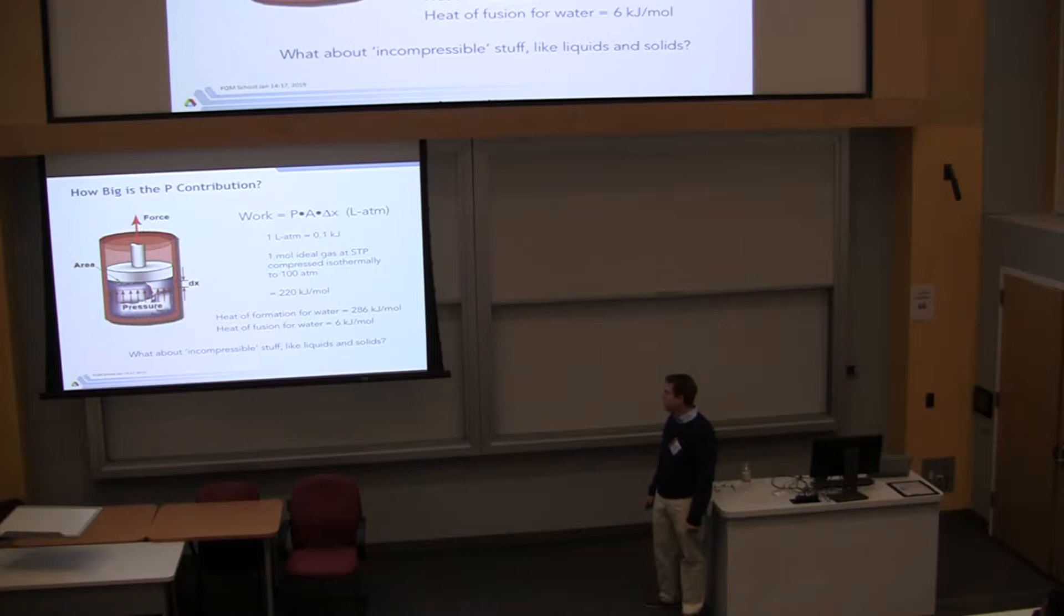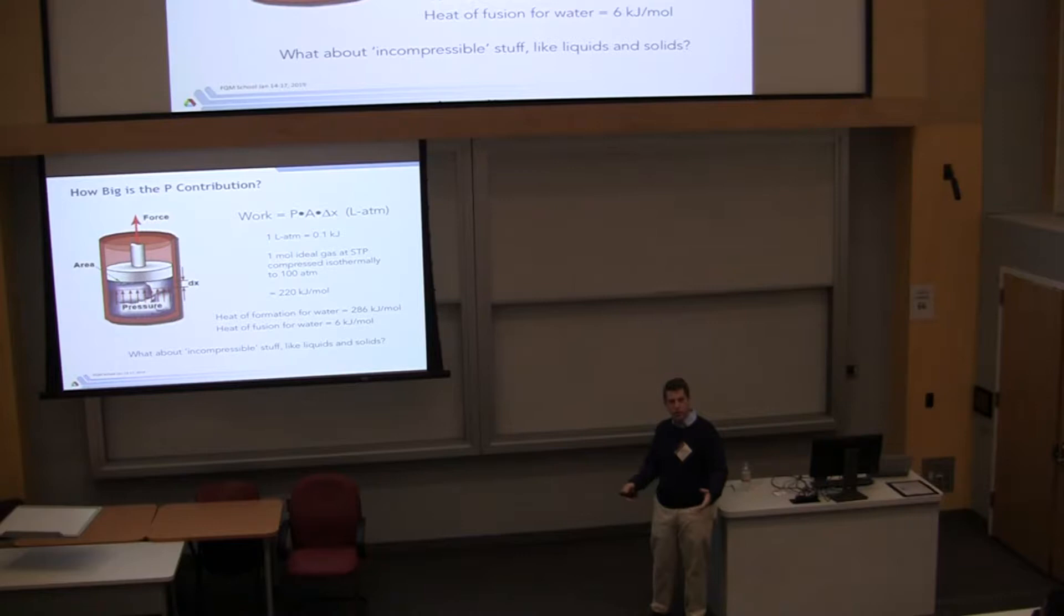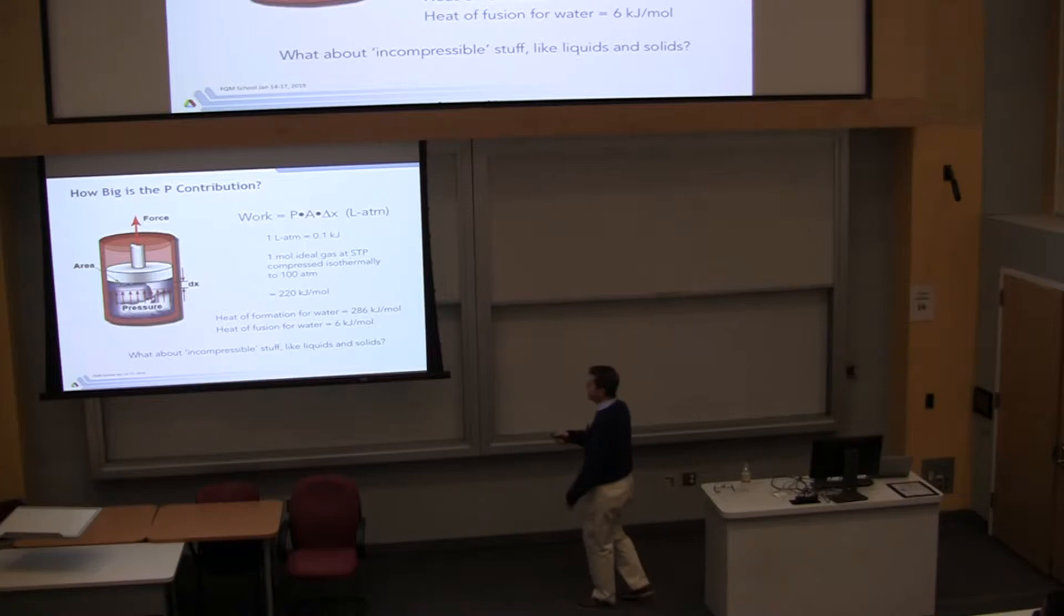It involves a few terms here. The simplest one when you think about chemistry, there's an enthalpic term. This is delta H. This is the endothermic versus exothermic. There's an entropy term, which, of course, at high temperature, entropy starts to win. This is the reason why David pointed out correctly that these high temperature growths, you get more defects and ingrowths and problems because the entropy starts to raise its ugly head.